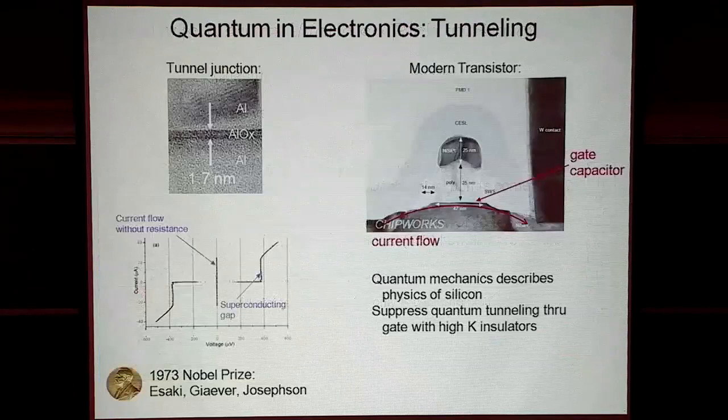Okay, so I've been talking about atoms. Let's talk a little bit closer to the field with electrons. Electrons in a metal have wave properties too, and this Pauli exclusion principle actually is very important in describing how metals work. I'm studying in my devices something called a tunnel junction, where you have electron waves that are forming in this aluminum. And then what we do is we grow a very thin aluminum oxide layer by just putting oxygen into the system, which naturally oxidizes the surface, and then evaporating aluminum on top.